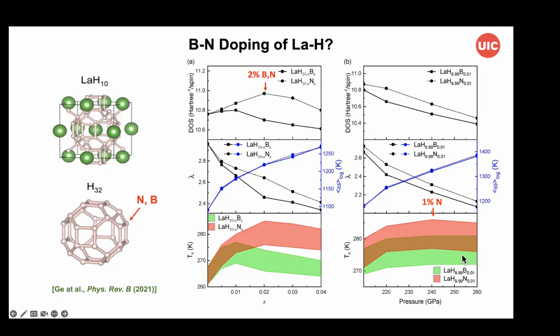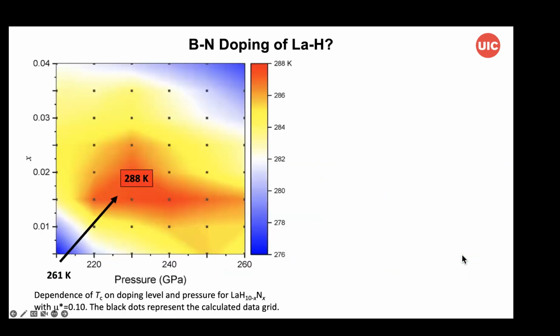In fact, the maximum for nitrogen doping was about 1% at 240 GPa. So we have this other plot now for the doping level versus the pressure, and we see the Tc increasing, which is sort of calibrated at 260 Kelvin going up to 288 Kelvin. So in agreement with what we see experimentally, at least a consistency argument that perhaps we have boron or nitrogen doping. In this particular case, it's the nitrogen that's most dominant.